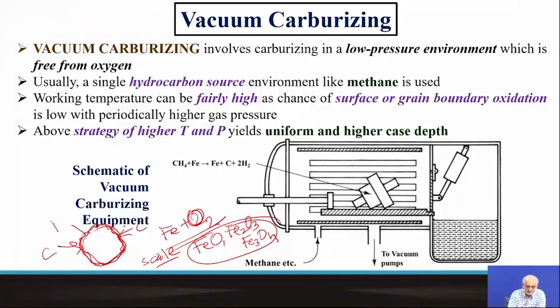Also, presence of oxygen will create another difficult or disadvantageous condition, whereby carbon from the bulk can actually try to diffuse out, react with oxygen, and form carbon dioxide or carbon monoxide. That means instead of carburizing, you end up doing decarburization.